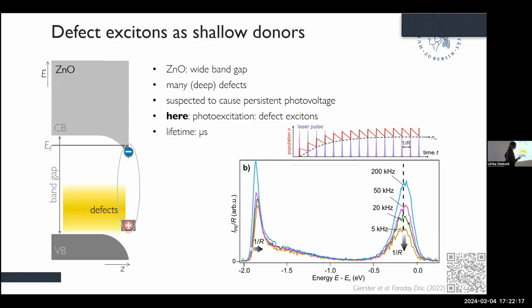So this means the pulses come at a microsecond difference. And so what we are creating here are more and more defect excitons that have a lifetime that exceeds the inverse repetition rate of our laser system, so that we end up in a photostationary population. We always have some defect excitons in our system. And when we change the repetition rate, the intensity changes because the photostationary state is a different one.